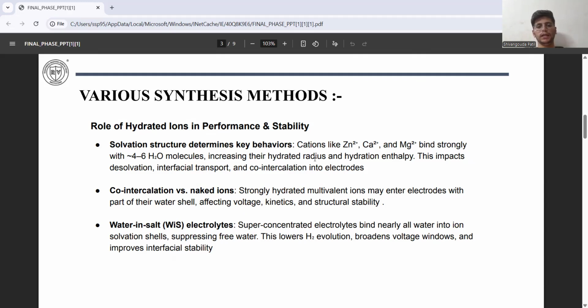Co-intercalation versus naked ions: strongly hydrated multivalent ions may enter electrodes with part of their water shell, affecting voltage, kinetics, and structural stability. Water in salt electrolytes: superconcentrated electrolytes bind nearly all water into ion solvation shells, suppressing free water. This lowers H2 evolution, broadens voltage windows, and improves interfacial stability.